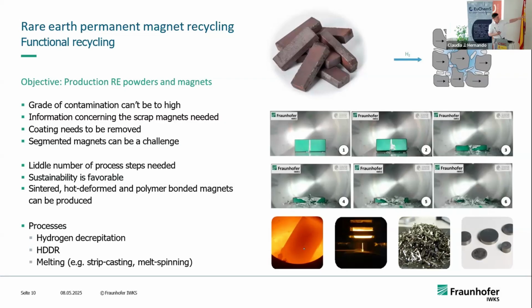You see here on the top how hydrogen is incorporated into the magnet, creating tension and stress. Due to the hydrogen incorporation, you basically powderize your system, and this powder can then be remilled, reused, and a sintered magnet can be produced out of this powder. Another way to go is melting the material. During melting, some of the oxide is also removed. This material can be transferred into hot deformed magnets, polymer bonded magnets, or sintered magnets. However, the melting step also consumes energy, which can be skipped when one starts directly with hydrogen decrepitation.